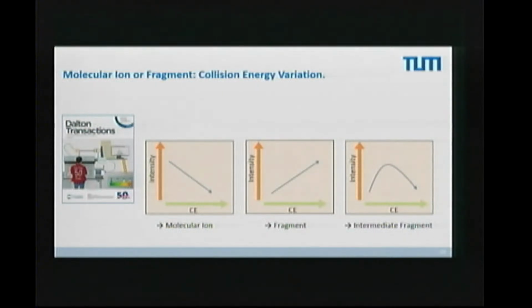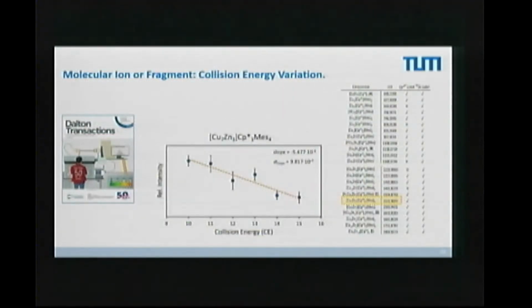So I have to give a lot of credit to my students, because it's brute force work. Every peak has to be assigned. And if we do that, we get this kind of list. And all these lists have been assigned. For example, I take out this one. This is the Cu7Zn3 Cp*3 mesityl4. And this is a molecular ion because the intensity goes down when we raise the collision energy.